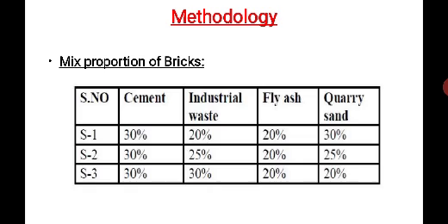Then comes the methodology. Mixed proportion of brick. The mixed proportion used for this experiment is as in this picture: cement 30% for sample 1, 30% for sample 2, 30% for sample 3. Industrial waste: sample 1 20%, sample 2 25%, sample 3 30%. Fly ash: sample 1 20%, sample 2 20%, sample 3 20%. Quarry sand: sample 1 30%, sample 2 25%, sample 3 20%.